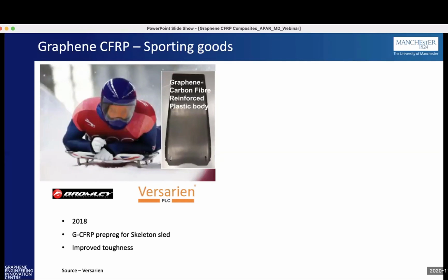So another area where graphene prepregs have been used is sporting goods. The athlete you see here, his name is Dom Parsons. He's a British Winter Olympian. And he won the bronze medal in the skeleton bob in 2018 on a graphene enhanced skeleton sled. So what they found was that the improved toughness helped with the dampening of the vibrations from the actual run through the runners into the athlete as well. So not only toughness, but the dampening enabled Dom to be more comfortable on the sled. It stopped vibrations, so he could control the sled a lot better.